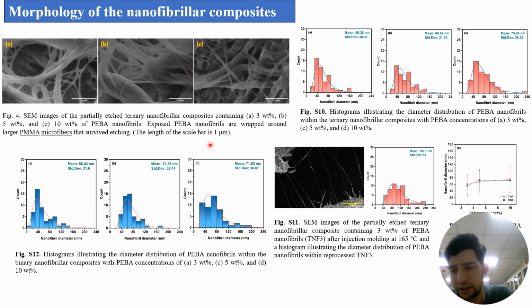So the results show that after etching with tetrahydrofuran, the PMMA microfibers were partially removed, revealing the PEBA nanofiber. The successful conversion of PEBA droplet into fiber is evident. However, it was challenging to distinguish EGMA nanofibers due to their similarity to PEBA nanofibers in size and interface.